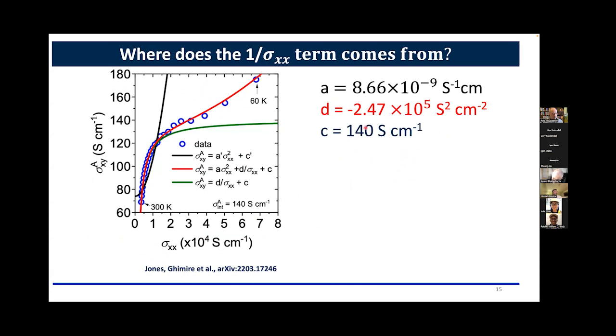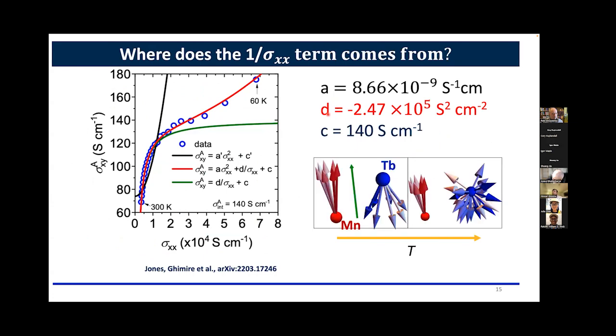Coming back to the question, what is this D term, right? We mentioned that there is a fluctuation here, and that we think this is coming from the fluctuating terbium moment. Now, in order to convince you, I will show you another material. The idea here is to get a ferromagnetic system along the C-axis, right? In ferromagnetic systems, we could polarize it, but it requires about 10 Tesla magnetic field. In the lab, it's pretty difficult to do.